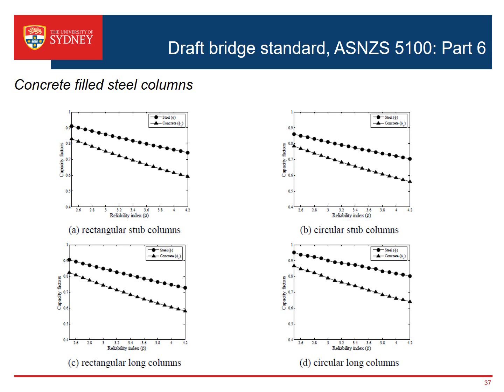Now for composite, there's a number of reasons for that. We also get confinement for concrete filled columns. We also find that heterogeneous shrinkage is lower in concrete filled columns, and so that ends up resulting in a higher compressive strength. But we've been able to show that if we kept the capacity factor for steel constant at 0.9, our capacity factor for concrete could be as high as 0.7 in some cases. We've looked at this for both rectangular and circular columns, both for short and for slender columns, taking into account issues associated with buckling and so forth. So we've made some suggested revisions there, and typically we'd be using a sliding factor for capacity factor of concrete in compression above 0.6 of what it used to be.